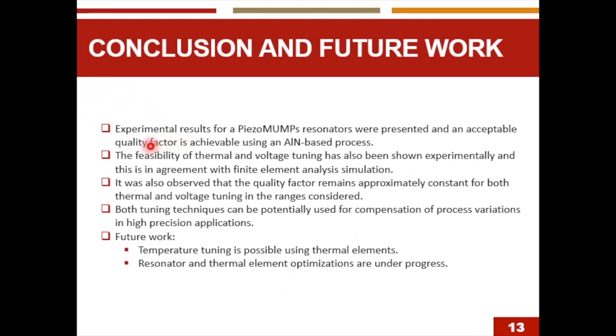Conclusion. Experimental results for PiezoMUMPS resonators were presented and an acceptable quality factor is achievable using an AlN-based process. The feasibility of thermal voltage tuning has also been shown experimentally and this is in agreement with finite element analysis simulation. It was also observed that the quality factor remains approximately constant for both thermal and voltage tuning in the range considered. Both tuning techniques can potentially be used for compensations of process variation in high precision applications.